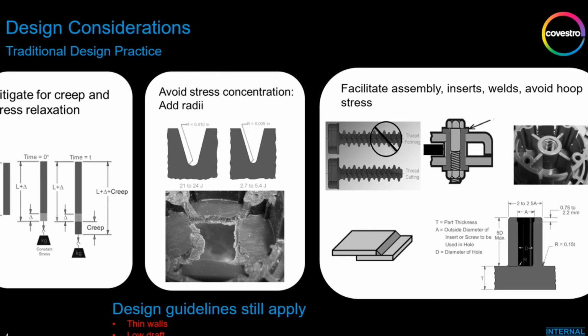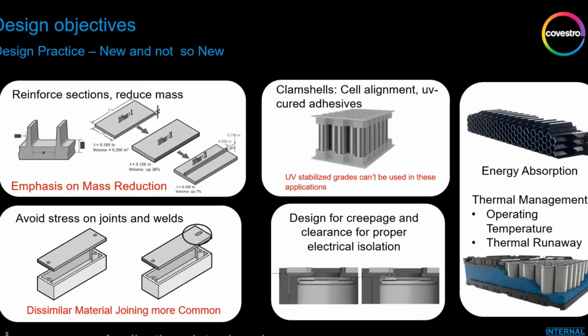We also have some other things that happen during the design for battery material or battery parts that we have to think about. Many of the parts that we look at in batteries are thin wall. So they're, I would say, thinner than what we would call traditional plastic parts. We have a lot of people designing parts that are 1 to 1.5 millimeters thick. This tends to become pretty thin wall for a lot of plastics. And then we also see in the same light that there has to be contact with mating components. So we often find that nobody wants to use traditional draft recommendations when they're making the molds. So we see thin walls and low draft quite often in battery parts. And there's ways to handle that with material and design, but you need to be conscious of those things and consider those up front when you're actually designing the parts.